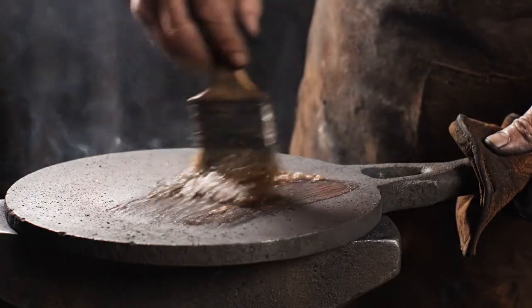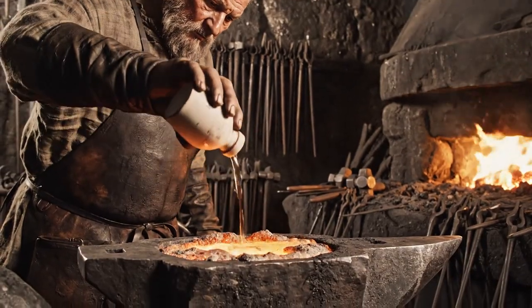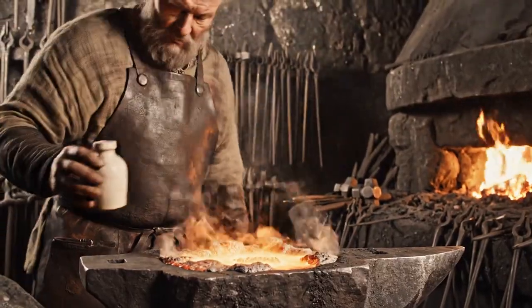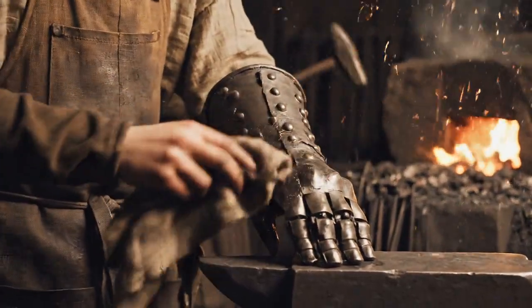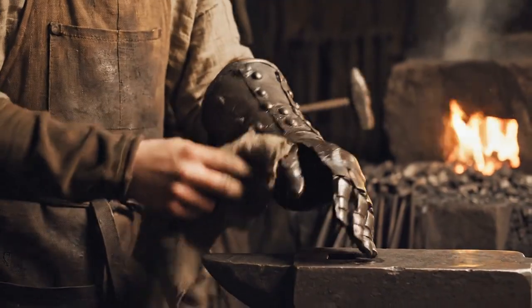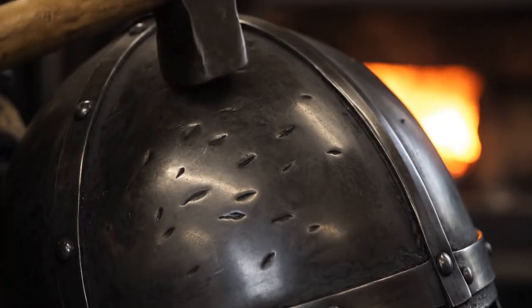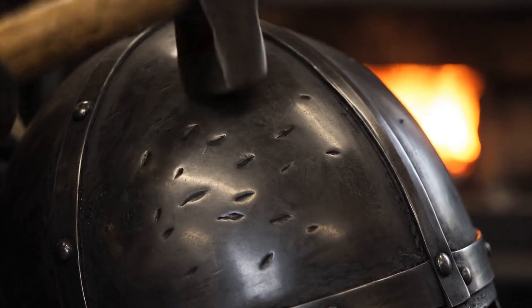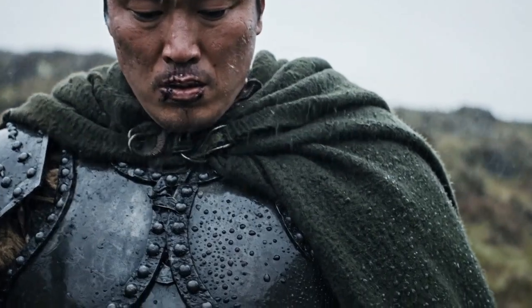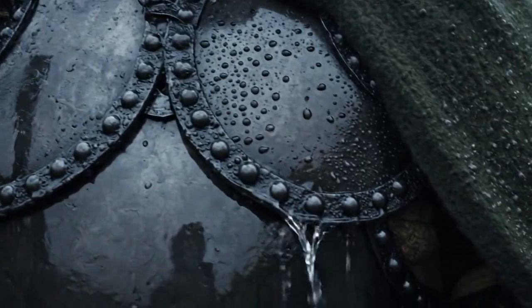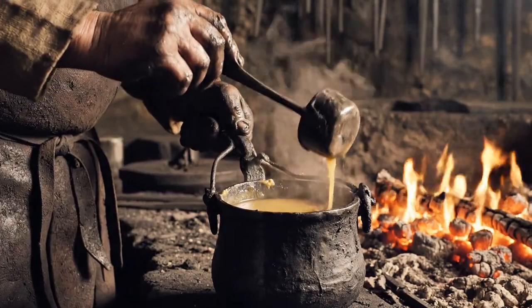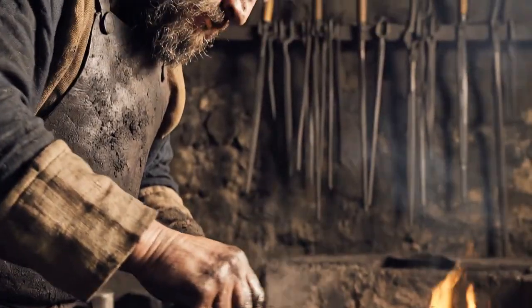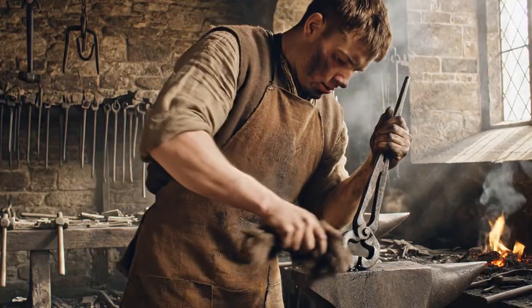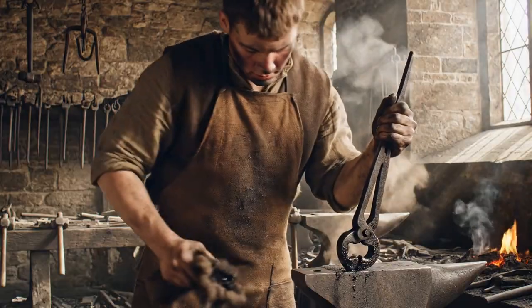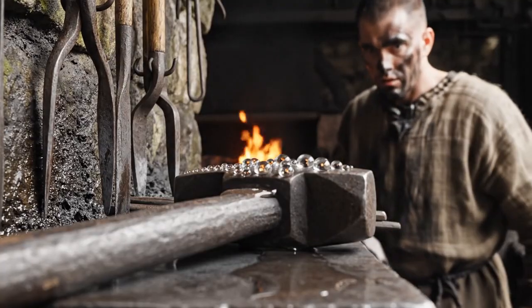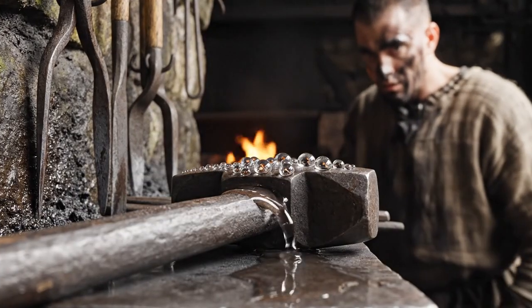A common traditional recipe calls for a mixture of 2 parts beeswax to 1 part linseed oil, melted together and applied to iron heated to approximately 215 degrees Celsius, 419 degrees Fahrenheit. The mixture of wax and oil fills the pores and creates a unified protective film. Some blacksmiths add turpentine as a solvent to thin the mixture and facilitate application, although this is not strictly necessary. The result is a finish that deepens the black color of the forge scale, produces a subtle satin sheen, and creates a surface that repels moisture with remarkable effectiveness.